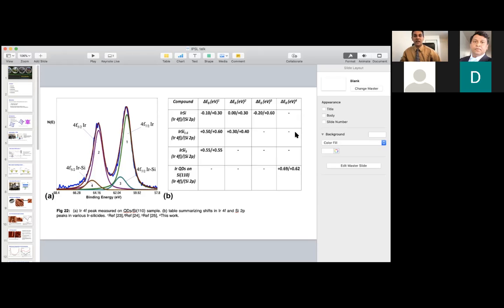The Schottky barriers for other metals like platinum and gold are around 0.3 electron volts. And iridium silicide is very special, because the Schottky barrier for holes is lower, around 0.17 electron volts, which is very suitable for IR detectors because we have to get the cutoff wavelength higher.